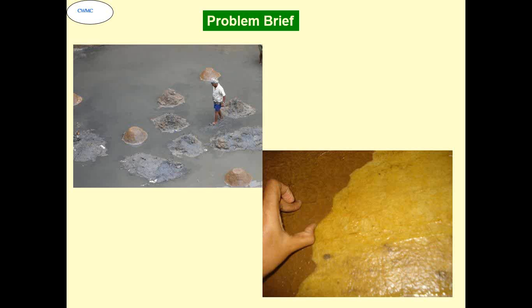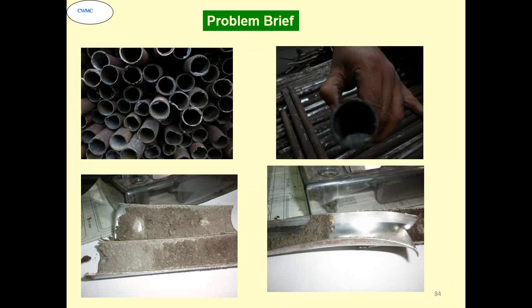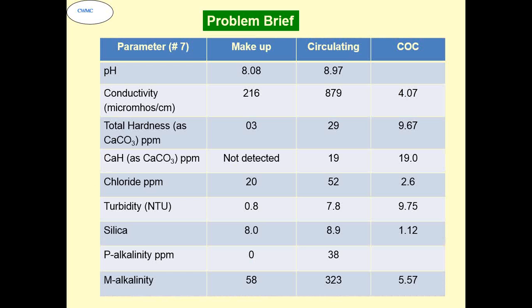See, this is the kind of thing what you see, the fly ash mounts inside that cooling water system. These were the tubes which were choked. You can see the fly ash inside the condenser tube, and when it was cleaned, you can see at one place it was shining, at the seam weld there was corrosion. These are the characteristics which were changed by the fly ash falling into the water. You can see the alkalinity, conductivity, everything changing because of the fly ash falling into the cooling water system.